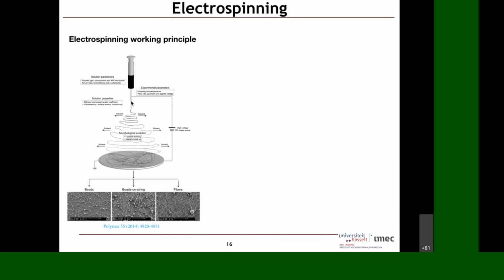It's called the Taylor cone, the same guy whose name I was mentioning. Then it starts bending and whipping, becoming thinner and thinner. And of course, the solvent is also evaporating. By the time it hits here, almost all the solvent is evaporated. And based on the characteristics of the polymer, how long the polymer is, what the concentration of the polymer is, what kind of solvent we use, we either get beads, or beads on string, or we get these fibers. And of course, my aim was to get this fiber. So I had to use either high molecular weight polymers, which are very, very long, or use a slightly higher concentration of the same material.